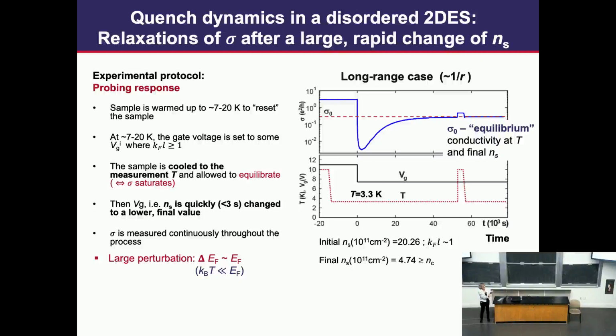And we track the evolution of conductivity with time. You can see that the conductivity at time equals zero drops because we reduce the number of carriers, but it doesn't stop at this reddish line, which is the equilibrium value. It overshoots it in this case by more than an order of magnitude.